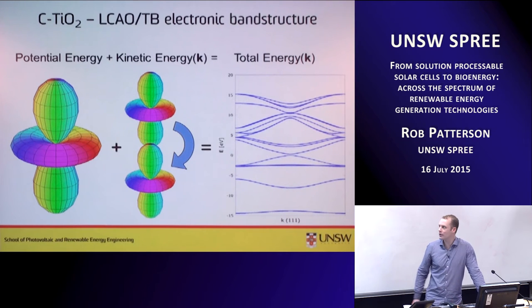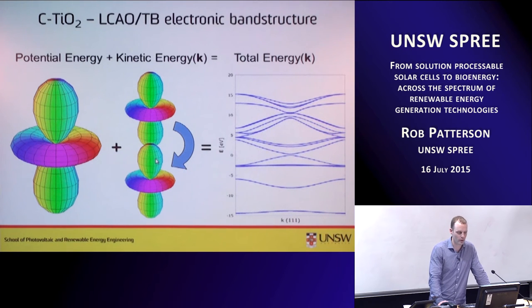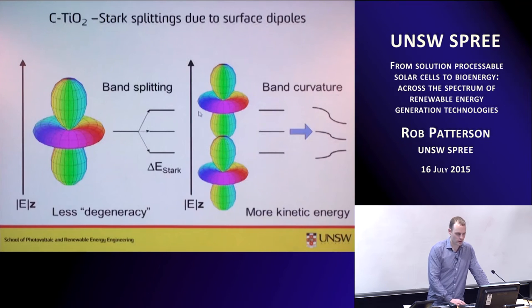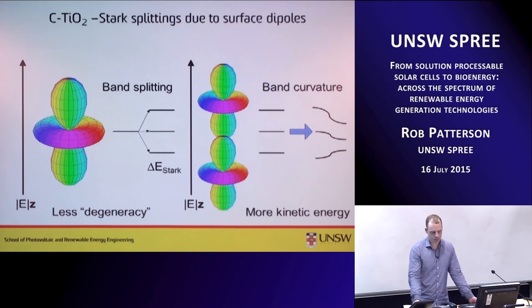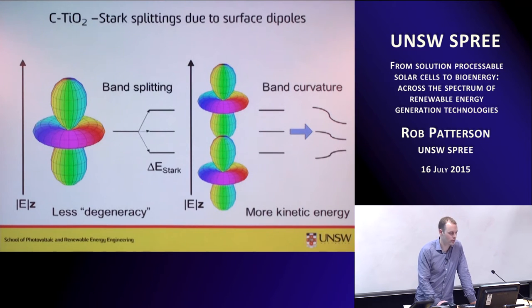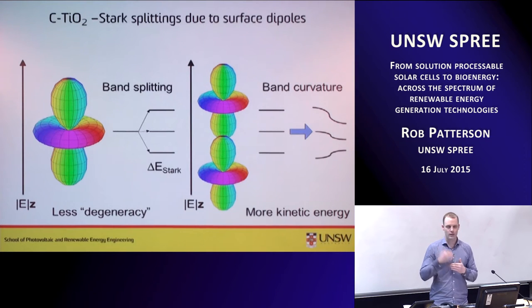So what I did was I wrote down a tight binding model where the electron states are broken down into hydrogen-like orbitals, look something like this. They have a potential energy and a kinetic energy, which is a function of k, the momentum or the wave number in the material. And if you sum these things up in a big matrix and you use the right coefficients and diagonalize it as a function of k, you can make band structure plots. And if you apply electric fields to these hydrogenic orbitals, there are ways, established theory telling you how to do that, then what you notice is that there are band splittings and increased band curvature as a result of the surface dipole.